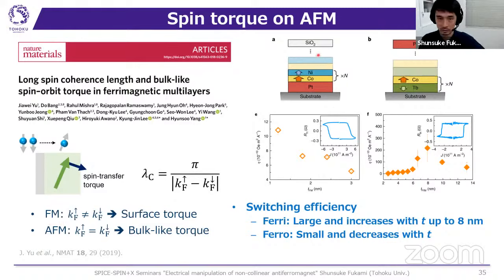And they carried out an experiment. So they prepared two systems. One system has the ferromagnetic cobalt nickel, and the other system has the antiferromagnetically coupled cobalt terbium multilayers, which was capped by platinum. And indeed, the switching efficiency, which is the coercive field divided by the threshold current density, decreases with increasing the thickness of the ferromagnetic layers for the ferromagnetic systems, but it increases for the ferrimagnetic systems. And also the magnitude of the efficiency is much larger for the ferrimagnetic systems.